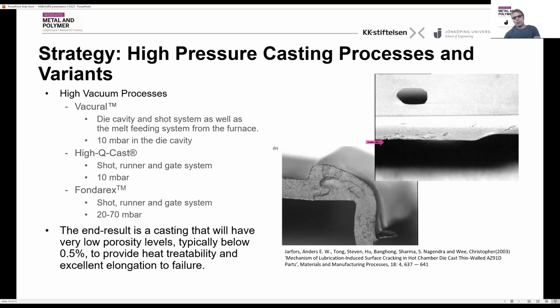At this point, you can see you have a bubble trail moving through in the same direction as the fill direction. And these little bubbles, they have been pickled. We pickled away the surface so that we could reveal these types of porosities that you would find. And this is one of the problems. So vacuum does not really solve all the problems, but you also have issues with die release agent and the use of that. So when you want to do high integrity casting, you end up with a very complex situation. I will come back to that. You can take the next.